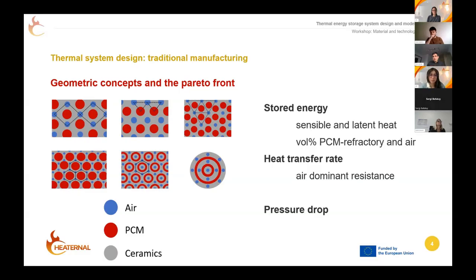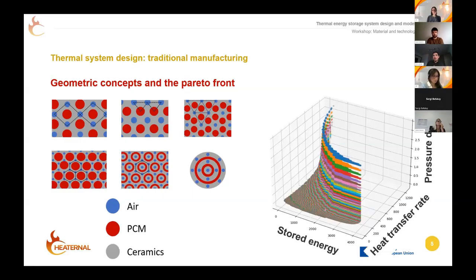Now, besides these two classic variables, you also have stored energy. So how much energy can you store? What's the thermal mass of your system? And that is where our PCMs come into play, where you have the latent heat, which you want to be as high as possible. Secondly, our geometry will define how much volume percentage PCM you can have compared to the refractory and air. If you compare those three variables for one of these systems, you get these type of Pareto